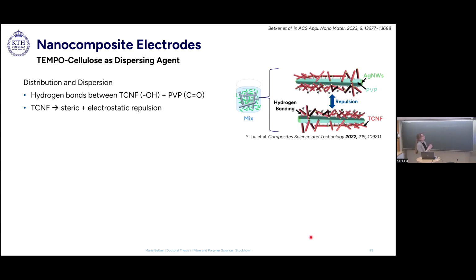So we have here, again, the silver nanowires in green. They are coated with a polymer called PVP. This has something to do with the synthesis of the nanowires. It doesn't matter right now. What matters is that this PVP polymer has carbonyl groups. So the carbonyl groups can actually form hydrogen bonds with the hydroxyl groups of the cellulose. So what can happen is that the cellulose arranges itself around the silver nanowires. And what we have then is, on one hand, steric repulsion, because we have the cellulose in between the nanowires, but we also have electrostatic repulsion, because the cellulose is negatively charged.